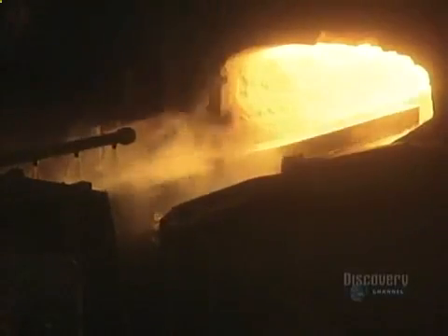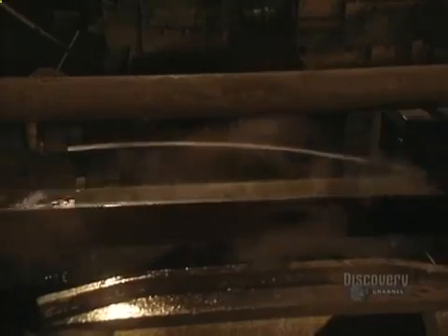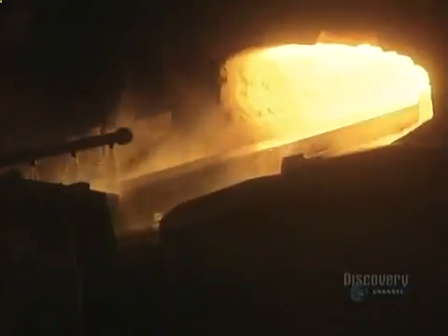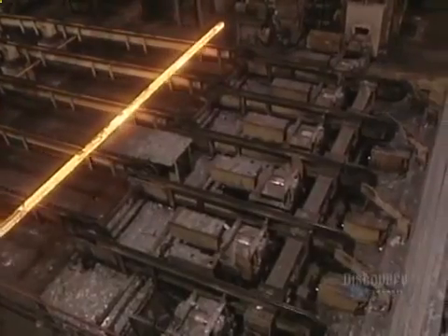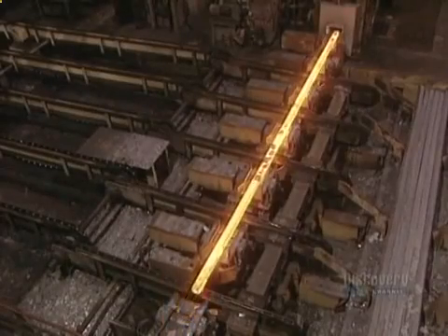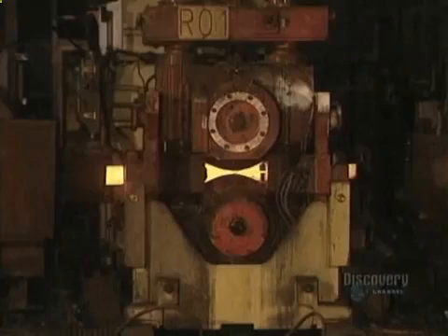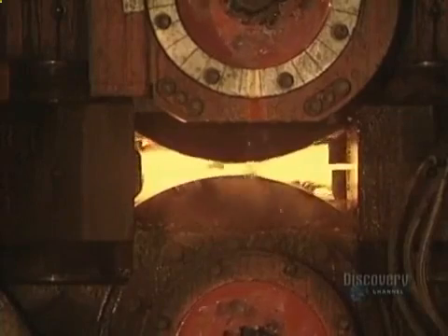Before flattening begins, billets are placed in the furnace to be reheated for 2 hours at 1095 degrees centigrade. Water jets cool the billet ejector. The billets are placed on the flattener, where powerful rollers compress them. This operation gives the billets the required shape and size. Water-cooled rollers crush the billets.